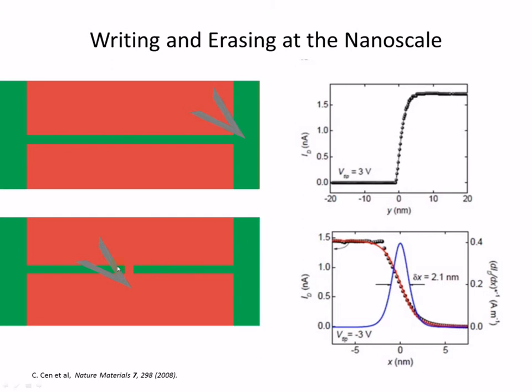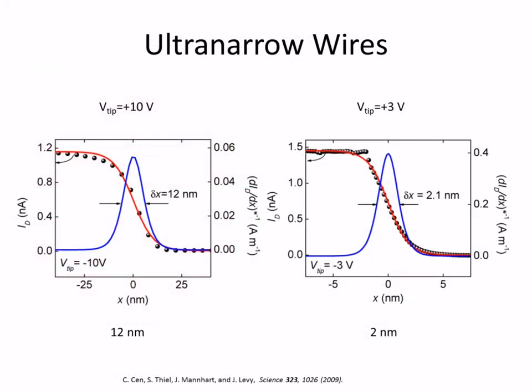And the structure that we created here, using plus 3 volts and minus 3 volts, allowed us to create a wire that was only 2 nanometers wide. So by changing the tip voltage, we can make the width of the wire go from 12 nanometers with 10 volts down to 2.1 nanometers with 3 volts. And these are the widths for wires.